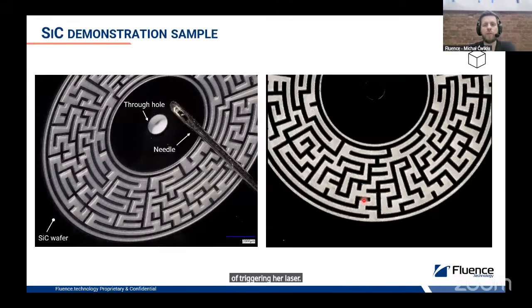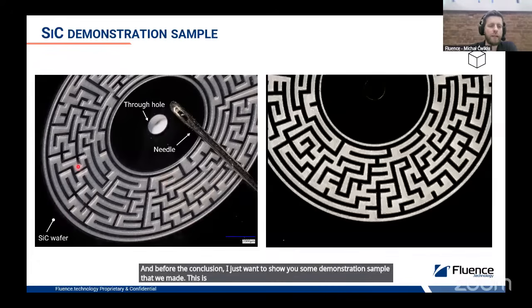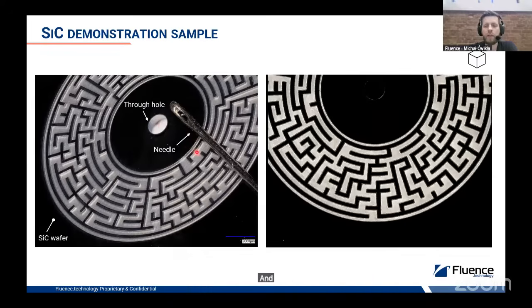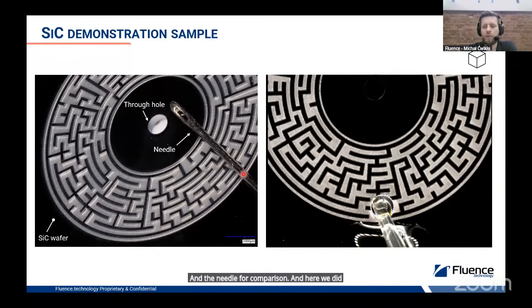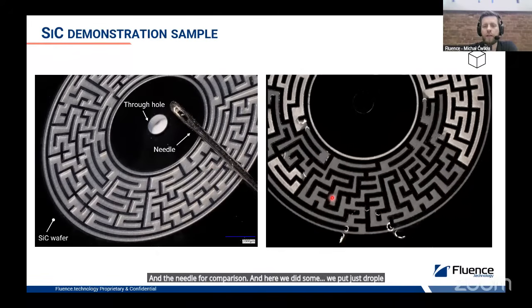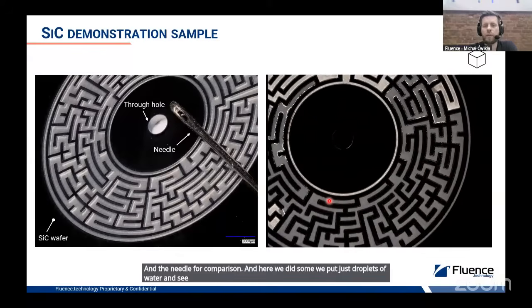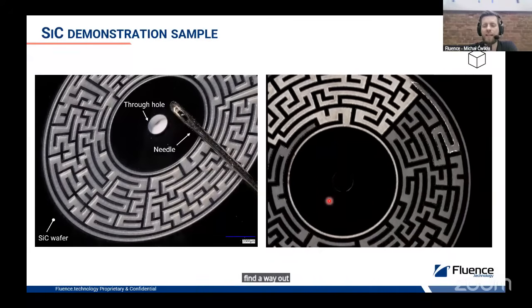And before the conclusion, I just want to show you some demonstration samples that we made. This is a SiC wafer, and this was ablated to form some kind of labyrinth and a through hole in the top, as you can see, nice, no taper, and the needle for comparison. And here we put just a droplet of water and see if it could find a way out, let's say.